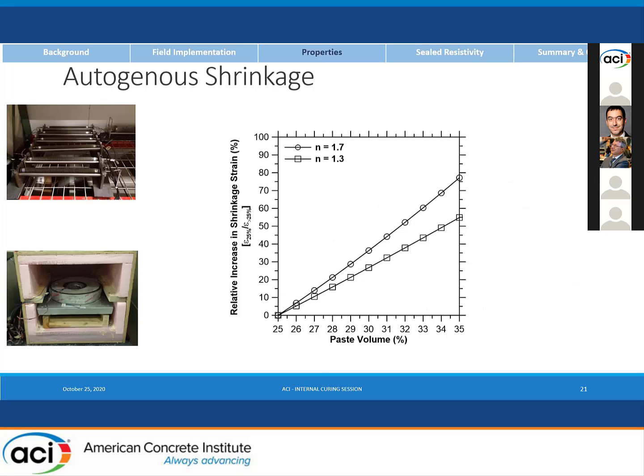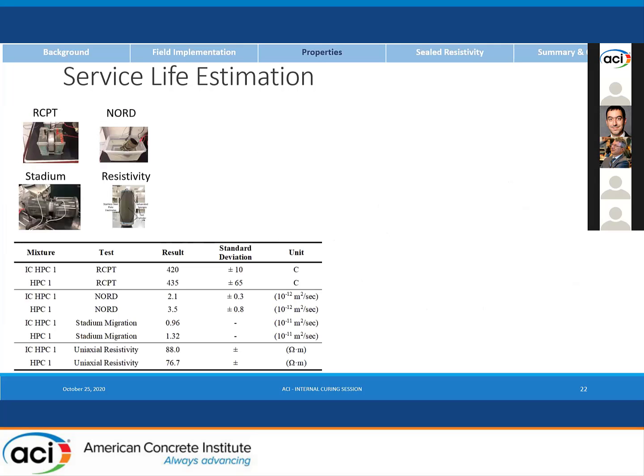Getting into the actual service life portion of this, we went ahead and ran all of the tests that are being considered for durability specs. And I'll just simply point out that all of the units for all those tests are very different, and so it does make it sort of difficult to look at. I will also point out that we blew right past the 1500 threshold. So these were indeed well within specification and quite high performance materials.